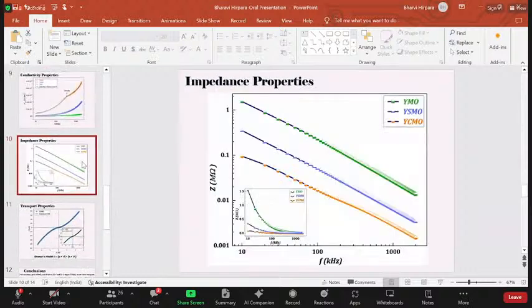Now we have the impedance properties also. Here, the plot shows the variation in impedance with frequency for all the three compounds. For all the three samples, impedance is found to decrease with increase in frequency, which can be ascribed to the field-induced enhancement in energy attained by charge carriers, thereby conduction gets enhanced and the resistance part of the impedance for all the three samples gets suppressed.